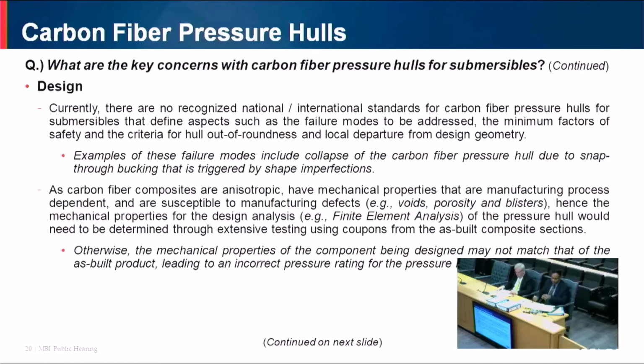Okay, so the other thing is when you do your design calculations for carbon fiber composites, these materials are anisotropic. That means the mechanical properties vary with direction. The mechanical properties through the thickness may vary. Okay. And they're also dependent on the manufacturing process. So all of these can vary the mechanical properties of the finished product. So when you do your design calculation, it's very important that you test coupons from the as-built product. How this is done is you will typically extend the length of the cylinder. Okay, this is called prolongations. And from there you will cut coupons. Coupons are basically samples of material that you then send to a lab for testing.